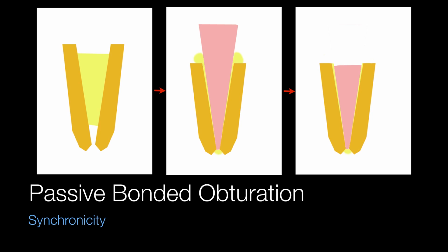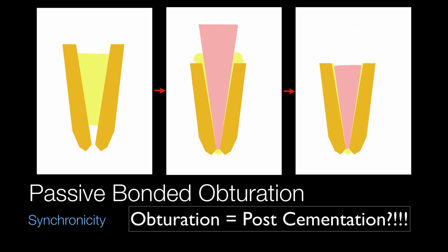You can directly inject it into the canal the way we've described as the advanced protocol, or you can place it on a little pad and then gently put it into the canal all the way to the end. If you do inject, make sure you have a microscope so you can see how much you're injecting and don't overfill the canal. The idea is to only fill the upper half of the canal and then push the sealer down with a file to the apex, then coat your cone and place it all the way down to the end of the root. This kind of technique is really the kind of cementation that you would have using a post. So this is a passive obturation technique.